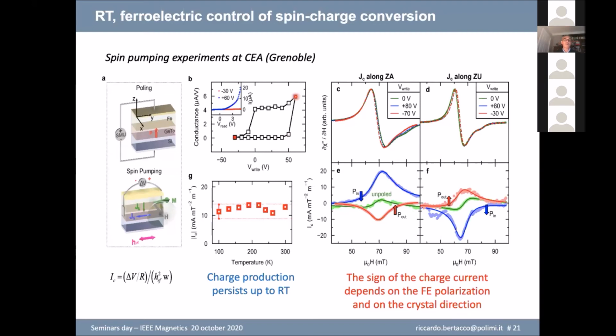So you know in which state you are when you measure. And this is the typical measurement. In this column, you have the case of a slice cut along the ZA direction, which is a peculiar crystallographic direction of germanium telluride. This is a ferromagnetic resonance for different applied voltages. And you see here the interesting story: for the polarization pointing downwards, you have this blue curve